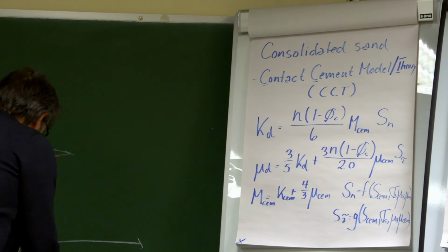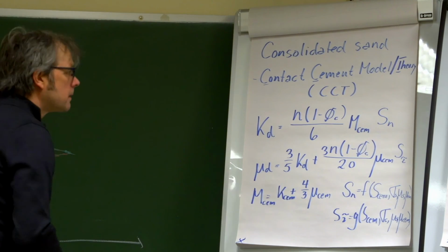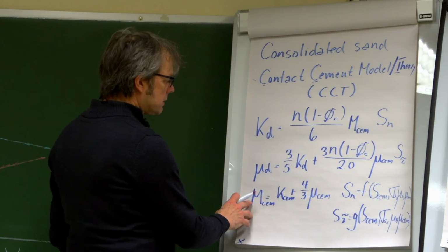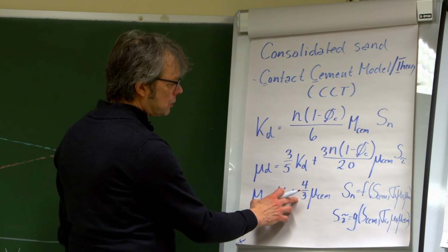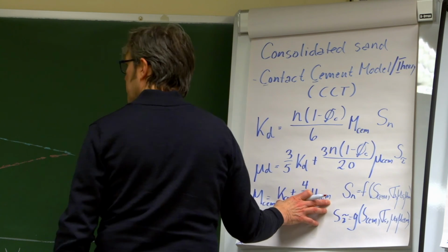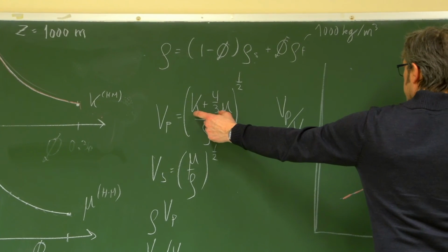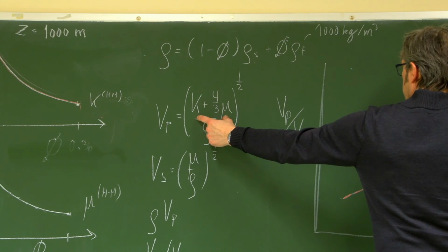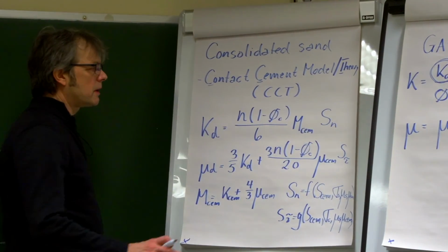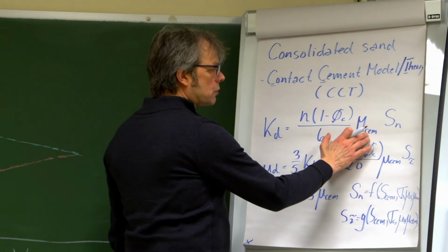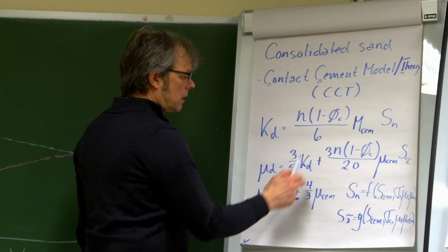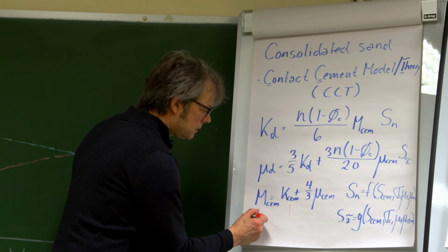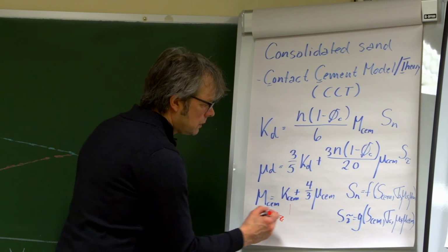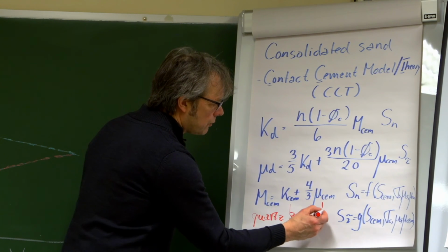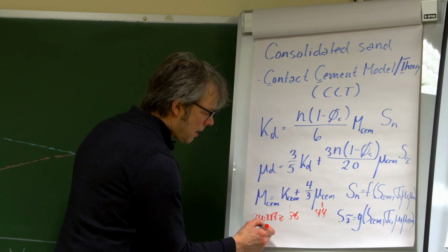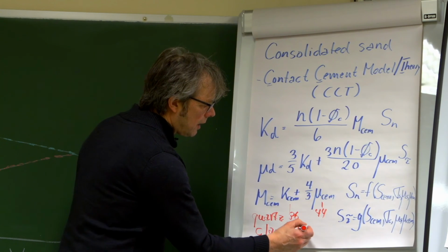So I could just define that, okay, this M modulus is simply the K, the bulk modulus, plus 4/3 times the shear modulus. And if you see in this formula here of the VP, it's just the numerator of the VP formula. So we very often call this a plane wave elastic modulus. So we see that we also need to know the bulk modulus of the cement. If it is quartz cementation, it's 36 here and 44 here. If you use clay, we use 21 and 7.